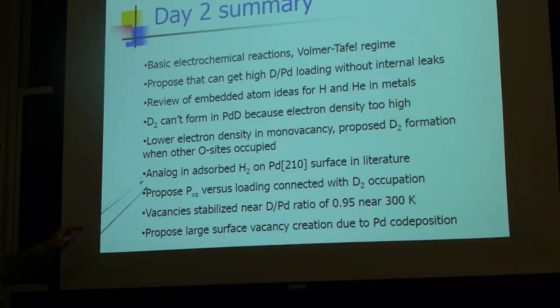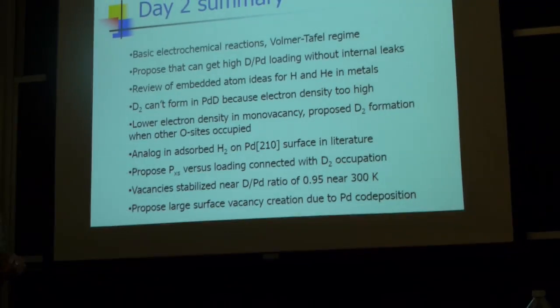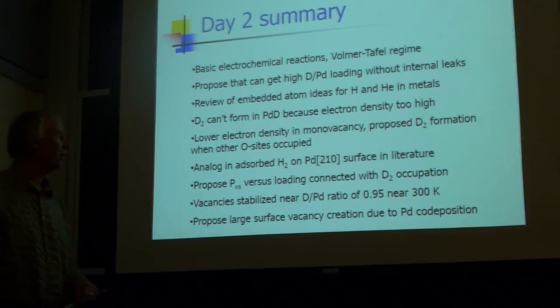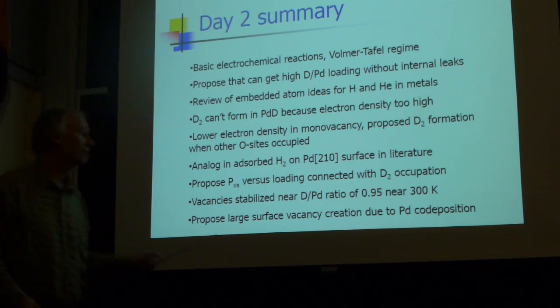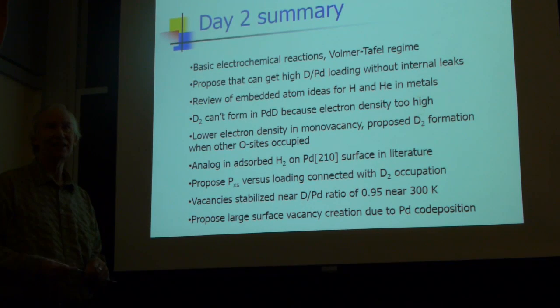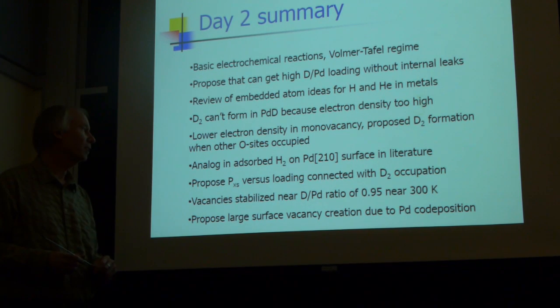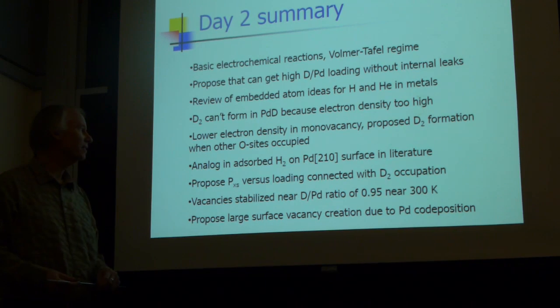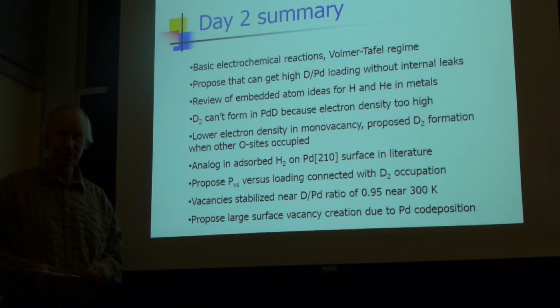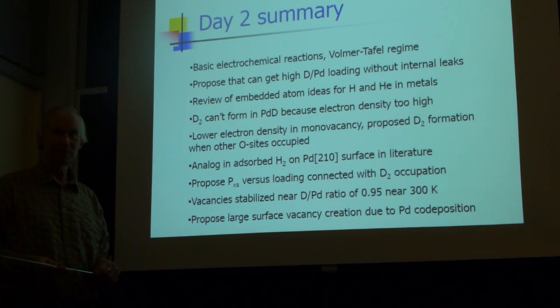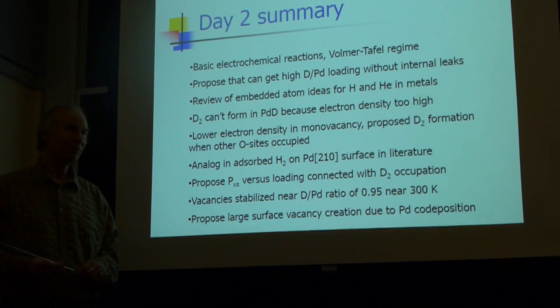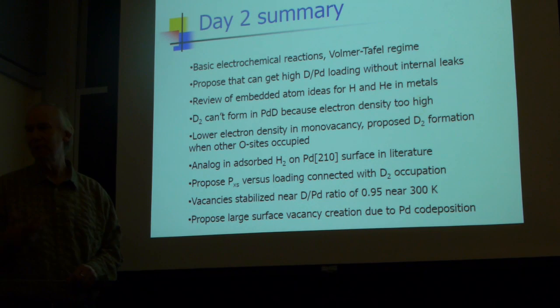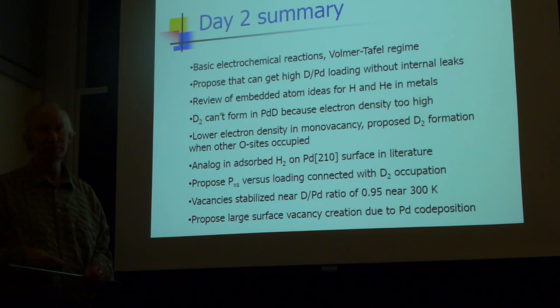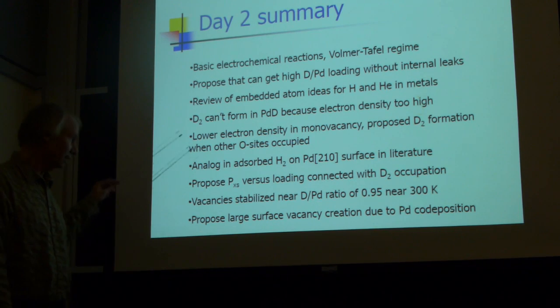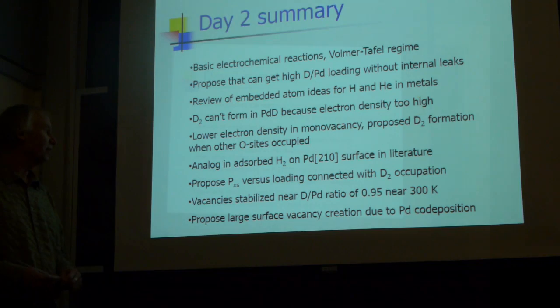It turns out in the literature, we've got an analog to the proposed state. The analog is a sigma-bonded molecular H2 state that's been observed experimentally and been calculated theoretically on the surface of palladium hydride, on the 210 surface. The binding energy we found was 270 millivolts, which from my perspective is a fantastic number, and is consistent with the energy, I think, of a sigma-bonded dihydrogen D2 state. So we proposed that excess power in the Fleischmann-Pons experiment was connected to D2 occupation.